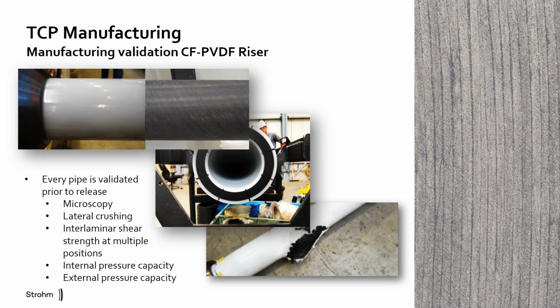Now, I've described a TCP platform, and the core of that platform is to provide a product that has been designed and manufactured to an extremely high standard. And that standard is maintained throughout and validated at every step in the process. Even though this is the case, we take extra steps during our production process. You can never fully design out the risk of unexpected events. We ensure that our manufacturing facility is treated like a clean room. We 100% visually inspect the pipe during manufacture, and we record every piece of data relating to the parameters and stability of our manufacturing process.